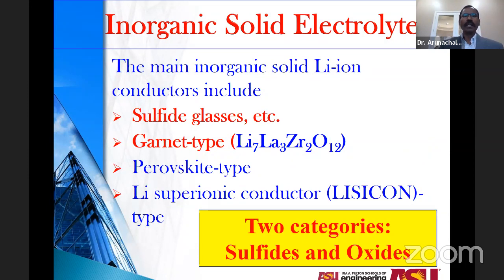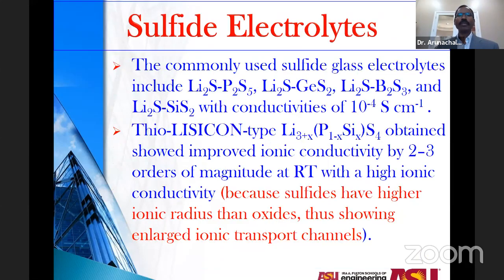The other electrolytes are certainly inorganic materials comprising sulfide glasses or garnet structure or perovskite, or also LISICON structure. Mostly the major categories comprise sulfides and also oxide-based solid electrolytes, which are being heavily focused on these days. For sulfide electrolytes, again, the commonly used ones are sulfide glass materials like lithium sulfide, phosphorus sulfide, or lithium sulfide, germanium sulfide, or lithium sulfide, boron sulfide, or silicon sulfide. All these materials would lead to conductivities up to 10⁻⁴ or 0.1 millisiemens per centimeter.